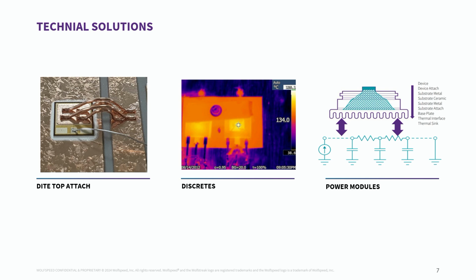many are still using discretes for certain powers, but when it comes to higher powers, you definitely need to go to power modules to get the full potential of silicon carbide, which you can also see here on the right-hand side. It's a thermal path from the device through the die attach down to the cooling path, which is super important. And the lower we run on temperature, the more power you get out of it. So cooling is also the key. Thank you.